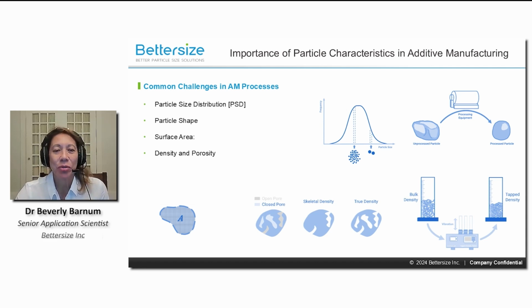Skeletal density and true density are related to the surface and interior structures of porous particles. Skeletal density is the ratio of the mass of the porous particles to the volume of the particles that excludes the open pores. True density, also defined as absolute density, is calculated such that open and closed pores are not considered in the volume of the porous particle. If there are no closed or sealed pores, skeletal density would be equal to true density.